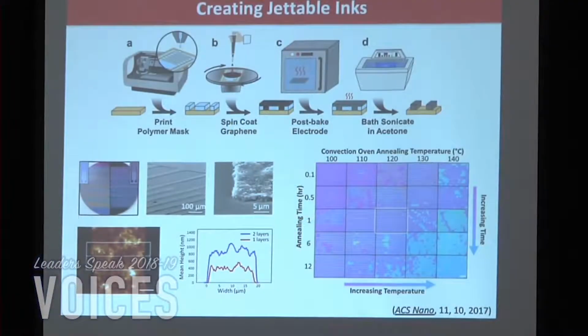And this is that technique. We print a polymer mask. It's kind of like an acrylic, kind of like a nail polish-like substance. We spin coat graphene. We optimize the post-baking process so that the graphene that wasn't on top of that nail polish-like substance stuck and didn't come off, but the nail polish-like substance still was able to etch away. And then we bath sonicate it or rinse it off in that sonicate bath or acetone bath that you saw. So doing that, we can make electronics.